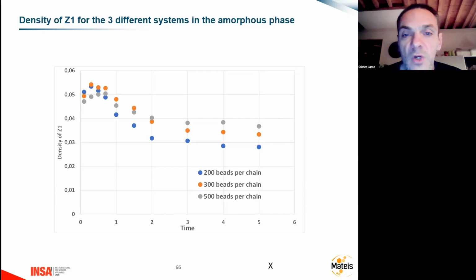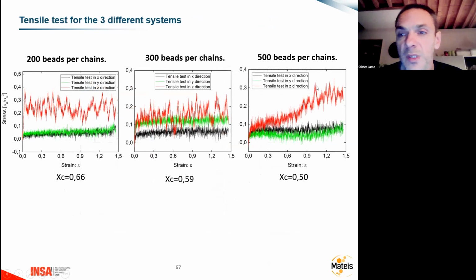If we look at the comparison of the mechanical properties, it's not so easy again to compare, but I will just forget the two y and x directions, which are very weak due to the crystallite. For the red curve, what we see is that when we increase the number of beads, the slope is slightly increasing, which is consistent with the fact that the density of entanglement is increasing. The yield is difficult to analyze, even if it's probably due to the crystallinity, which is not the same and which is much higher for this system. But we are on the way to connect the local topology in the amorphous phase to the mechanical properties.